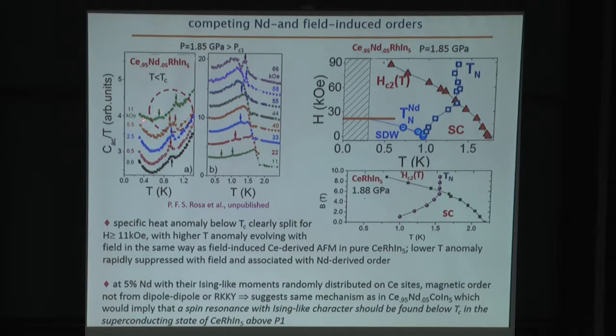And the field evolution of these anomalies is plotted in this field temperature phase diagram here, where this higher temperature field split anomaly is shown by these squares. And what I just want to point out is that the evolution of these open squares in this neodymium-doped sample is very similar to the evolution of field-induced magnetism in pure CeRhIn5. And so we associate this anomaly that gives rise to this phase boundary as being due to magnetism that's derived from the cerium 4f electrons. Then this would leave this anomaly at zero field and a small field that gets rapidly suppressed as being due to magnetism associated with the presence of a small amount of neodymium.